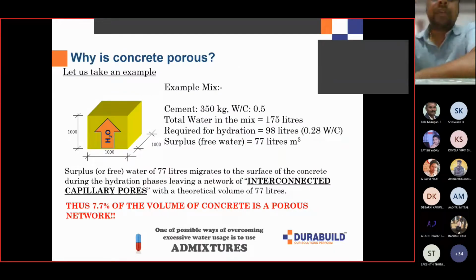Now, why is concrete porous? Let us understand that also. Let us take a typical concrete mix which has cement of say 350 kgs. The water cement ratio is somewhere around 0.5. So the total water in the mix will be 175 liters. Now, as per Neville, if you have read about Neville, and I am sure many of you have read about MS Shetty, the great MS Shetty, the amount of water that is needed for hydration is only a 0.28 water cement ratio, which comes out as 98 liters, needed for the hydration of the cement particles. But still we are adding 77 liters more water, which is also called the surplus or the free water.